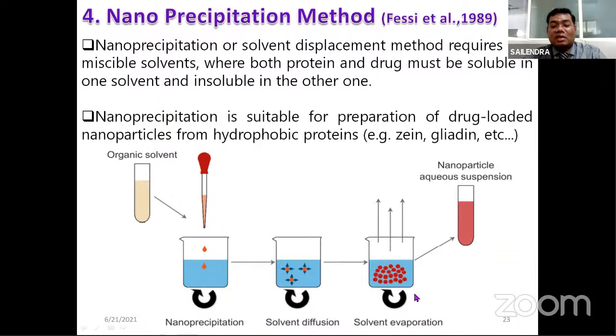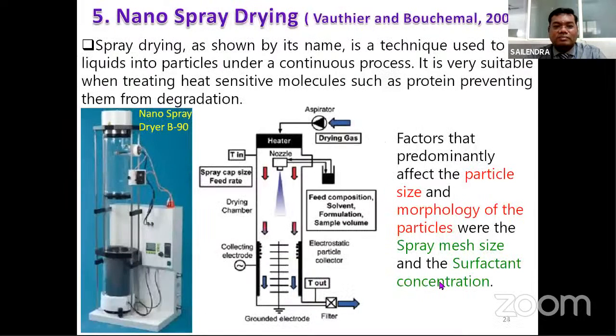That external solvent is going to get evaporated. So what is this blue solution you are looking at here? That blue solution will be evaporated, and finally whatever you are left with will be nanoparticles only. Now one of the demerits of this method is that when you are evaporating the solvents, you are treating the samples with temperature. This temperature can have an effect on the protein nanoparticles, even on the drug. So this is the least preferred method nowadays. We don't use this method for preparing these nanoparticles.